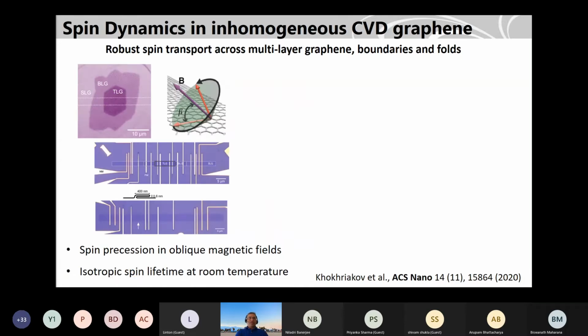So that's quite good. Then there are other issues. Our group is part of the Graphene Flagship, which is trying to develop graphene for spintronic applications in the European Union project. So we are looking at different problems existing with CVD graphene, especially because for scalable systems we need CVD graphene, not exfoliated. In some CVD graphenes, you can find multi-layer patches. For example, here is a large-area graphene over a wafer scale, but you will find patches around 10 or 20 micrometers at many places, like single layer, bilayer, and even trilayer. So there are multi-layer patches.